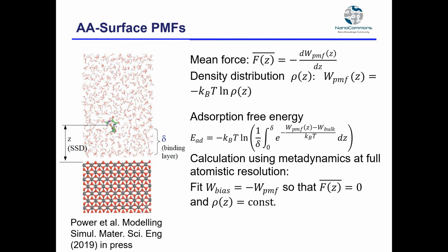Then the surface interaction now is the most detailed part of this, simply because it should take into account occasional hydration effects, which appear to be pretty important, and the orientation of the amino acid. So it is done using atomistic simulation. For the purpose of this tool, we use already pre-calculated potentials of mean force.